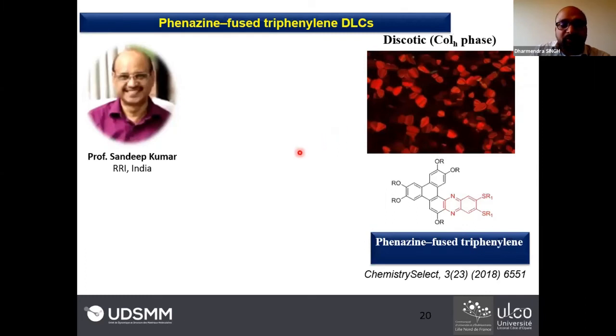Okay, so now we move to the next system. As I showed you in the previous slides, triphenylene molecules are very good organic electronic materials. So in the second term, we tried to attach a phenazine part to the triphenylene to see the effect on the charge transportation. One of the students of Professor Sandeep Kumar, Mr. Ashwat Gowda, who is now a postdoc in China, prepared this compound. He fused this phenazine compound to the triphenylene and prepared the phenazine-fused triphenylene discotic liquid crystals. It was a very good compound, and for the first time this compound shows that a discotic liquid crystal can show this mesophase down to room temperature.